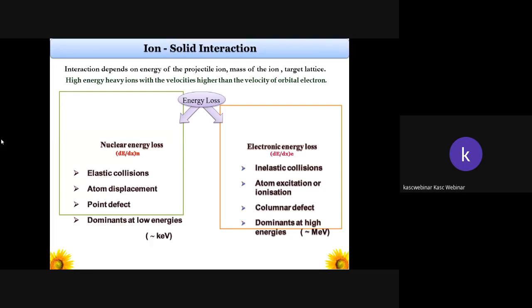But instead, if I choose a lower energy level in terms of kilo electron volt, elastic collisions are possible. So one can expect that nuclear energy loss may be possible in the kilo electron volt range. Usually it produces a little atomic displacement or even certain Frenkel defects. That's called a point defect, like a vacancy, a displacement of an ion, or interchangeable positions of atoms and molecules present in a sample. So this phenomenon is usually dominant at a low energy level.